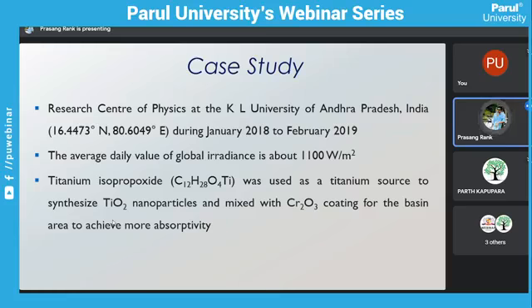What they did was use titanium dioxide nanoparticles mixed with Cr2O3 as a coating for the basin area to achieve more absorptivity. Titanium isopropoxide was used as the titanium source. So this mixture was used as the coating for the basin area. At the bottom of the area, they used this nanoparticle material to increase the absorptivity of